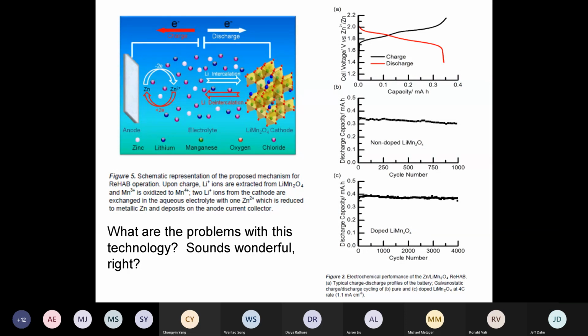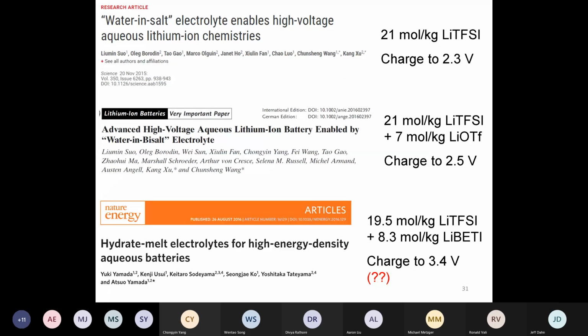So they use lithium chemistry in the cathode and zinc chemistry in the anode, which means the whole energy density will highly depend on the electrolyte amount, which will largely reduce the energy density of the full cell in real scale-up batteries. Okay, so that's pretty much every research proposed aqueous battery before we successfully extended the electrochemical window of aqueous batteries. So that leaves the next part.